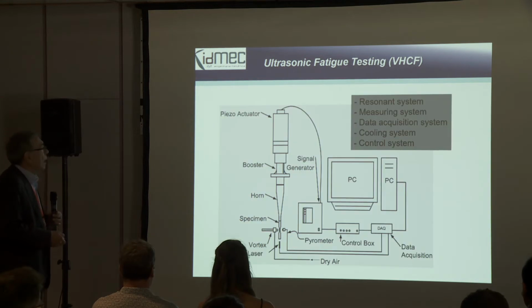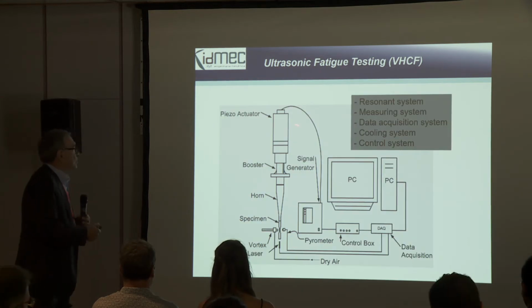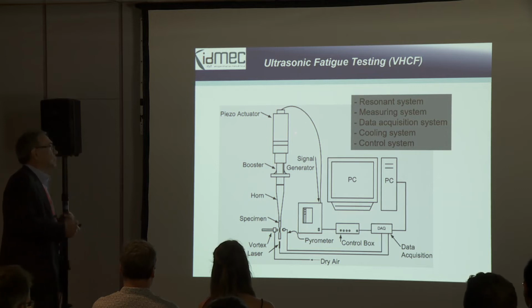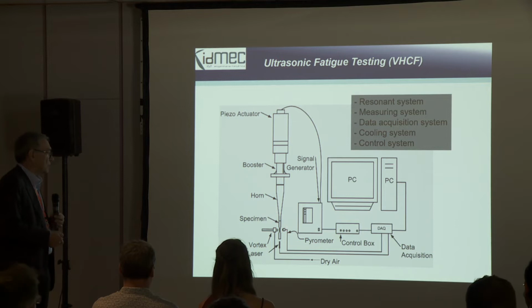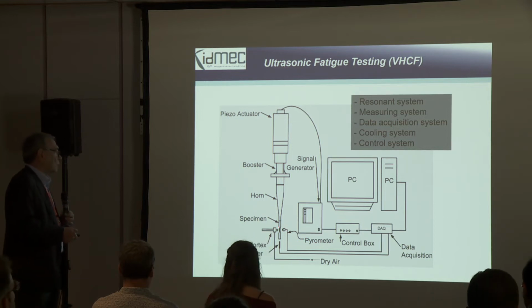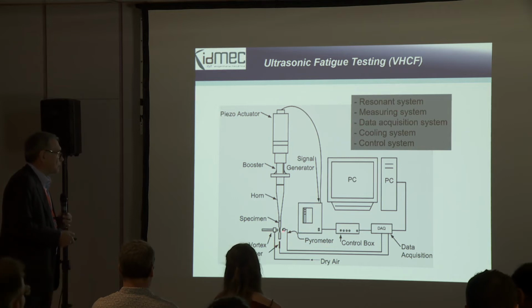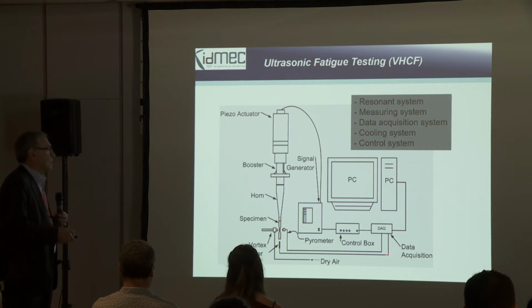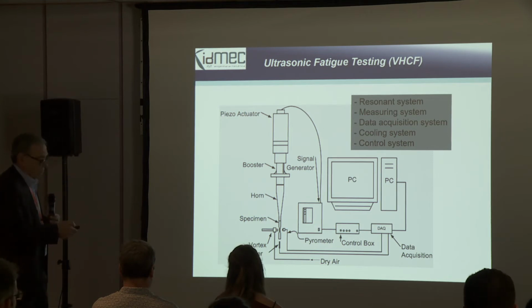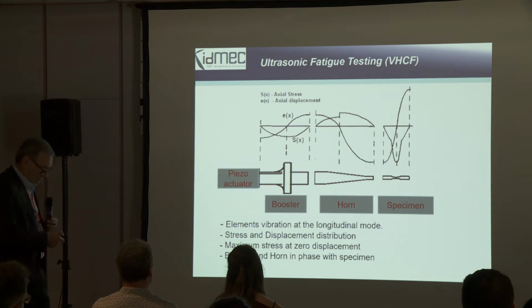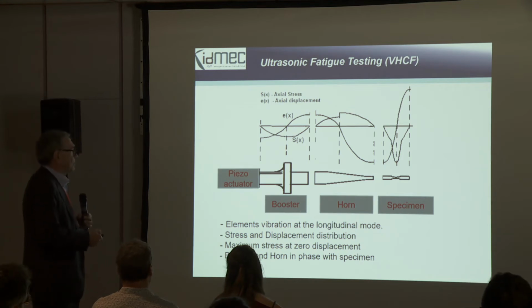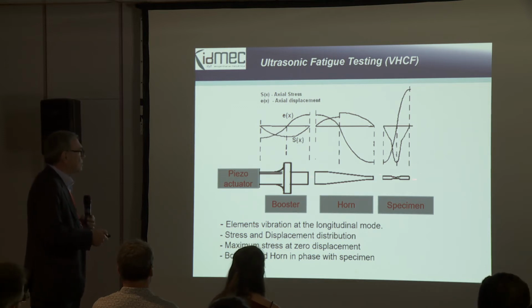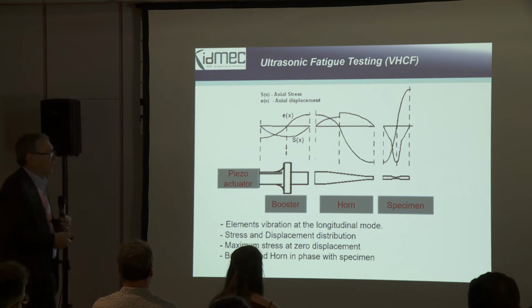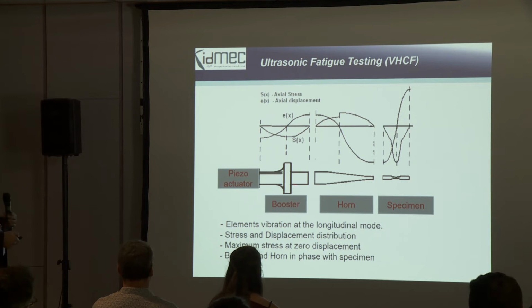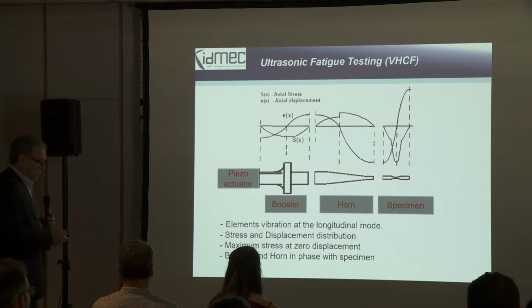So that's why the machines normally are composed of a piezoelectric actuator working at 20 kilohertz, a booster, a horn, and the specimen, and we have all the things: cooling, temperature measurement, laser measurement. Normally we put also strain gauges here, and we have the data acquisition system that everybody has presented before. And the idea is to have everything in resonance, either the piezoelectric actuator, the booster, the horn, and the specimen. So for axial loading, this is quite standard already. That's why I am not going to explain this.